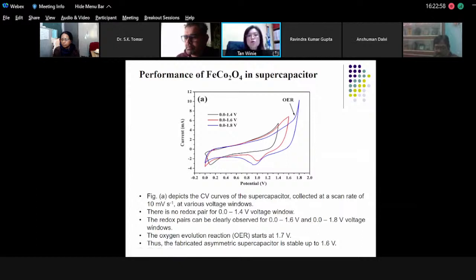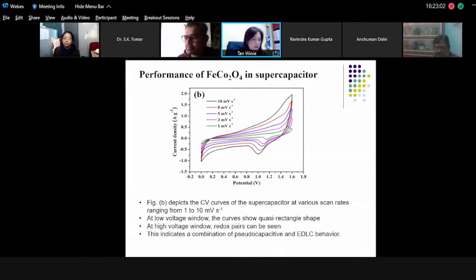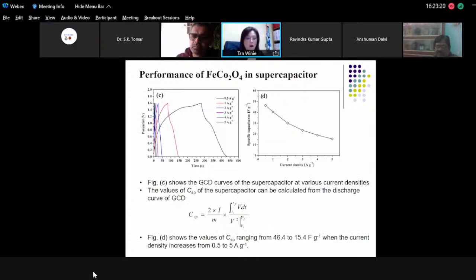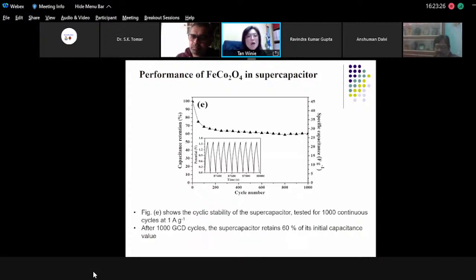We also do the CV curves at various scan rates. You see this is a very beautiful combination of pseudocapacitance and EDLC behavior because of the asymmetry. One end is the graphene oxide, the other end is the iron cobaltite, so it's a combination. This is the GCD curves of the supercapacitor. The most important thing is that after 1000 GCD cycles, our supercapacitor only retains 60% of its initial capacitance value, so we are working hard in the lab to increase the cyclability of these materials.